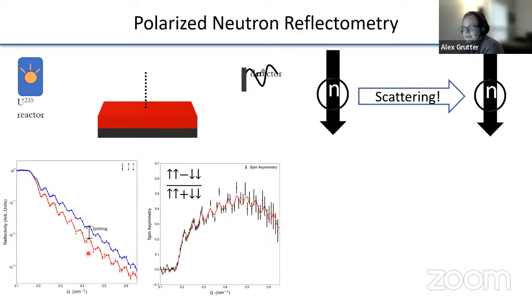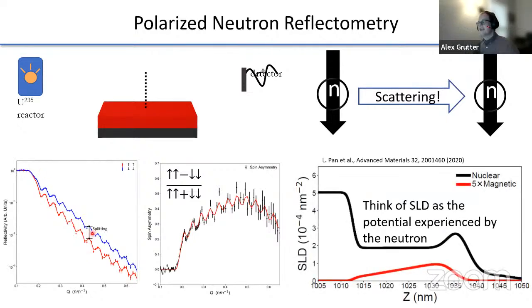Okay, so then we fit this data, and in the end, what you're trying to get out is a scattering length density depth profile. Now, rather than get into all of the detailed business of what a scattering length density is and where it comes from, you can think of it as the potential experienced by the neutron. And there are two forms of scattering length density we worry about.